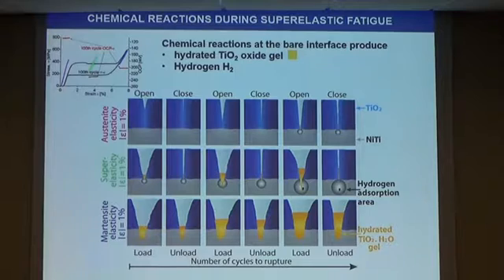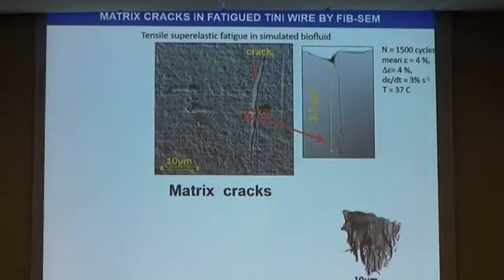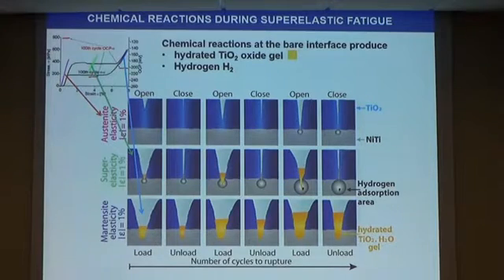This is a scenario I would like to use to explain why it happens. When you are in the elastic regime, it takes many cycles before the cracks make it down to the matrix. If you are in the superelastic regime, the cracks make it here, and you have this problem with the hydrogen production and the cracks opening and closing all the time. If you are in martensitic, the cracks are all the way open because the pre-strain is about 8%. So you have this gel, the oxide, created by the chemical reaction. It opens and closes, but there are not really many problems with the matrix. We believe this is the explanation, but there could be other explanations. I'm not absolutely sure about that.